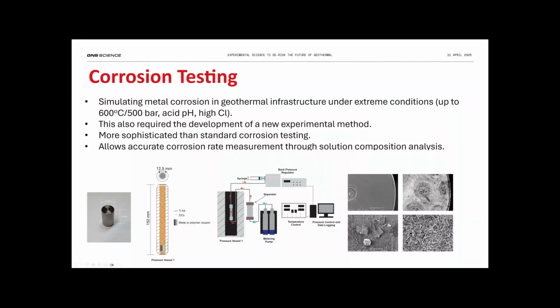And here you can see some examples of corrosion of carbon steel with a carbonate H2S solution. And these euhedral grains here are siderite crystals, and these grains here are pyrrhotite crystals. And this one on the top left here is the unreacted sample. This one on the right is the reacted sample. And so we're able to actually determine the actual mineralogy of the precipitates as well.